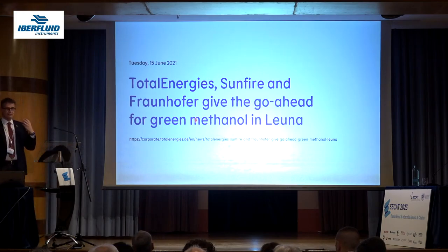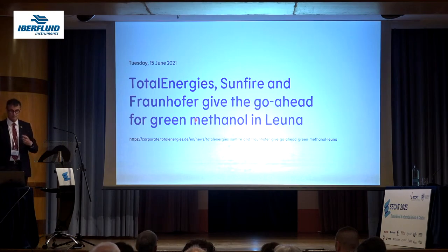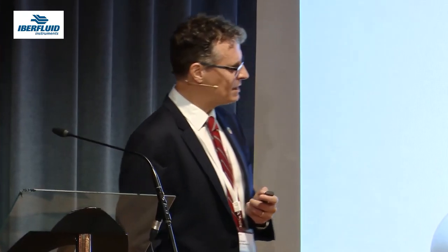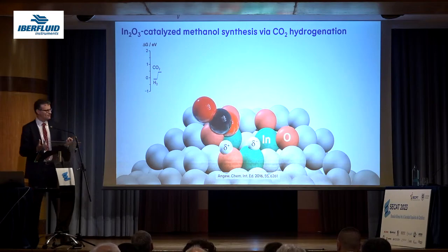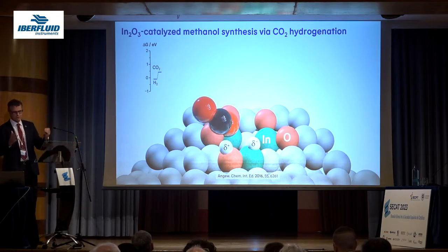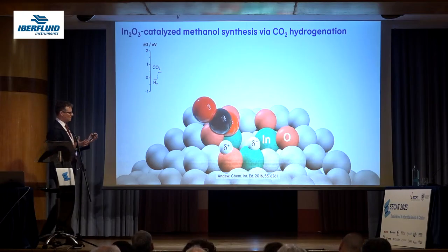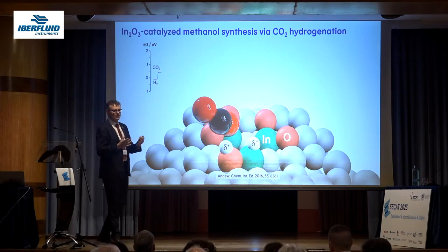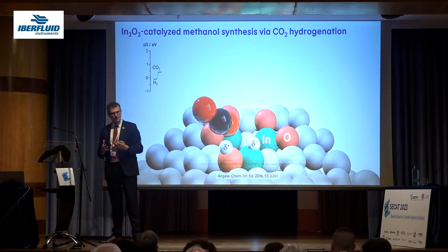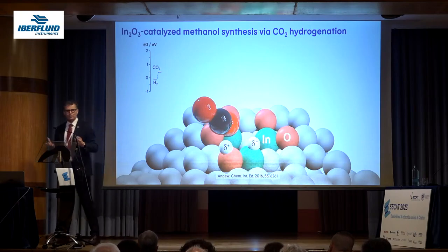And I also had the great luck to work with Total Energies in this project to develop the catalytic material for hydrogenating CO2. And this catalytic material is based on indium oxide, and I'm going to be a little bit fast here. This is about using vacancies for doing catalysis. Indium oxide is reducible. You could create vacancies on this indium oxide, and on these vacancies you can activate hydrogen and CO2 and do reactions on it.